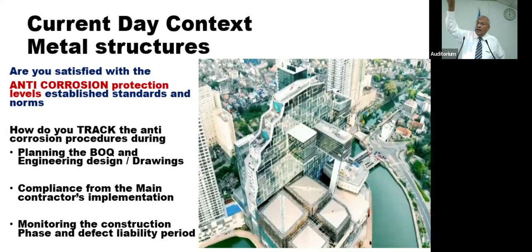So they go by the Delhi standard environment and put our railway stations as per Delhi. So whether Delhi or Mannar or whatever, if there's a standard to follow, like the paper I have given you, you should be able to use that and say, okay, my environment is this, I need this 320 microns. If you look at that paper, it says 320 microns. Now what has happened is, Delhi has only 150 microns, as per their standard. That is not enough for our country.